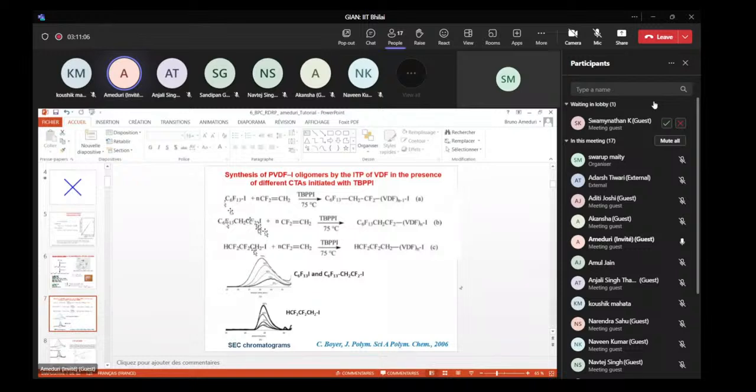So we did 3 reactions. We monitor the reaction by sampling, and we measure, of course, by NMR, by GPC, by TGA. We measure all the different characteristics, and we compare all of them of the resulting polymers. What you can see for the first 2 cases, we had some growing chain. Okay, so we have a nice regular increase of molecular weight, with a narrowing of the polydispersity. And this was already a kind of good feature to expect a possible trend of control.